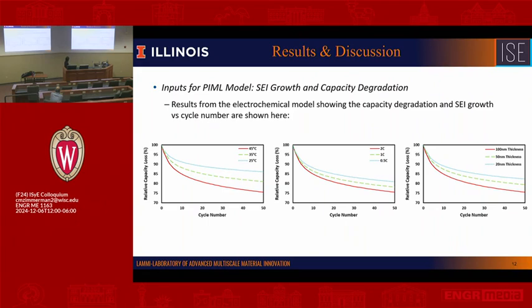So basically, for the temperature case, if we increase the temperature, there will be much faster degradation. That also means the thermal management can be very critical to the performance of the battery. For the charging, the 2C, 1C, and 0.5C represent the charging rate. So 2C, I think that mainly means 2 hours. No, that's not 2 hours, that's inverse. So 0.5C is the slowest charging, and 2C is the fastest charging. If we increase the charging rate, that also induces further degradation of the electrode.